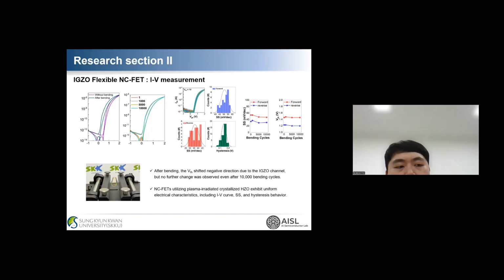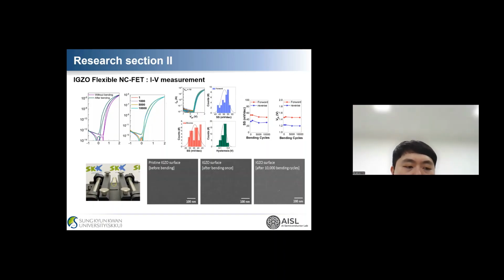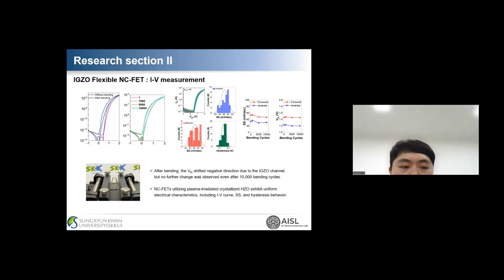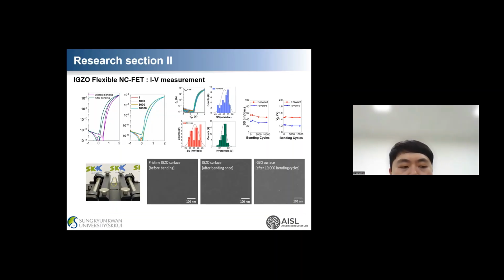As described in those studies, after the first bending cycle, we observed a negative shift in the turn-on voltage due to the characteristics of IGZO, resulting in the change in the threshold voltage. However, after that, the device shows stable operation with no significant degradation even after up to 10,000 bending cycles. Furthermore, we fabricated this transistor in an array formed on the flexible substrate and confirmed that the uniformity between devices was well maintained. In addition, the image confirmed that no cracks were observed on the surface.